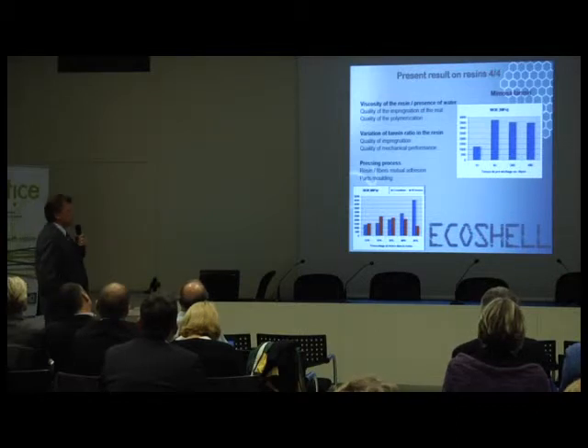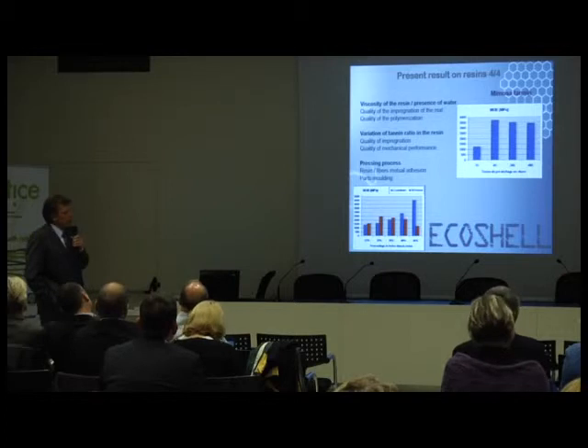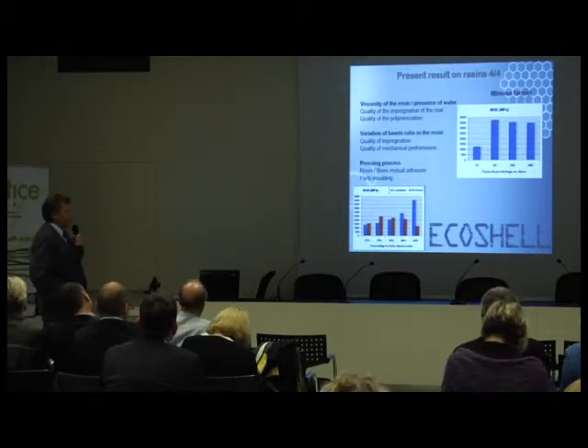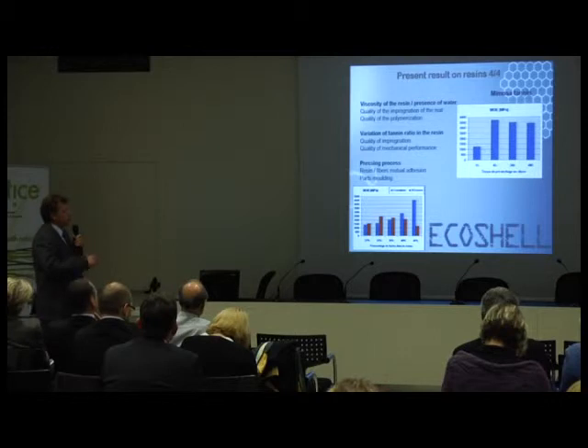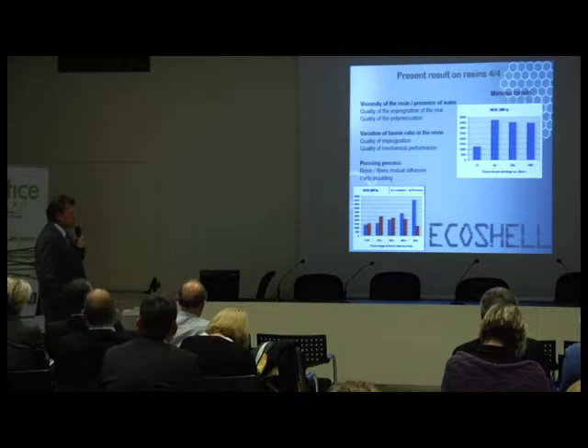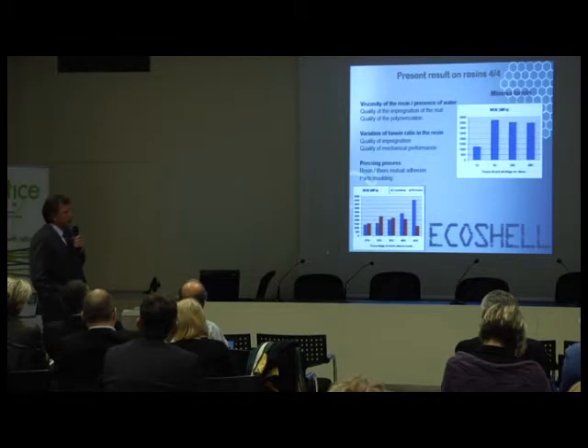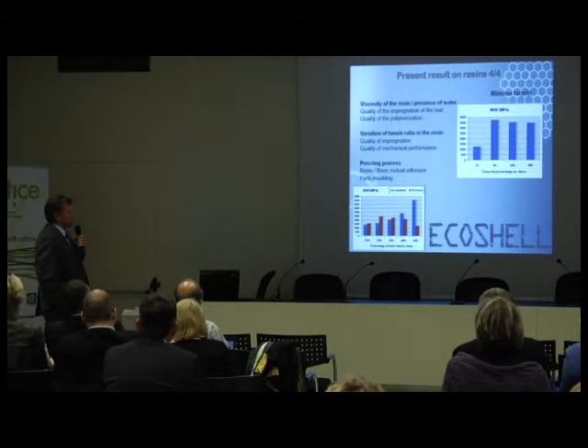But this resin looks very close to the furanic resin, and we think that even if today we do not have the solutions, it could be an interesting resin in matter of shock resistance. Because when we compare the two samples we had, the furanic resin is very fragile, but the mimosa tannin is more ductile. So a mix of those two resins could be a very good resin for our applications.